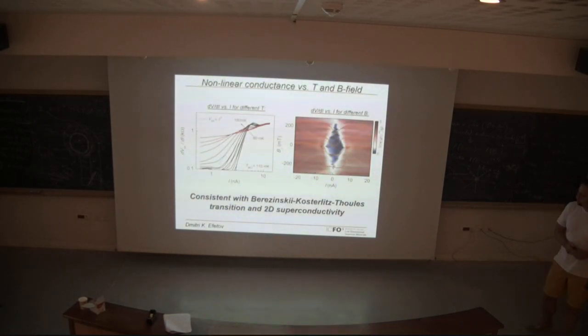And last but not least, we measure nonlinear conductance, DVDI measurements as a function of carrier density and excitation current. We can extract the typical critical current, on the order of only a few nanoamps. From this, we can also show that this transition is very sharp, and it is consistent with a BKT transition and with two-dimensional superconductivity. Of course, we can also apply a perpendicular field to the nonlinear conductance data, and we can see that the gap closes at 300 millitesla.